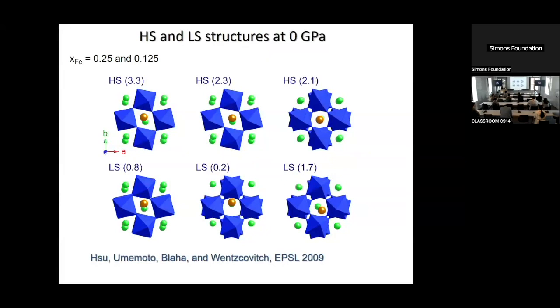And that's why the title of that paper in Science in 2004 was Non-Convective Layers in the Lower Mantle. Across the high spin to low spin state change, the gap opens from 1 to 3. That means infrared light can go through, so conduction through radiation is more important, and that damps the vigor of the convection. So that is the implication. This is an important problem too, figuring out what happens with the optical properties across the spectrum. That's a very cool problem.